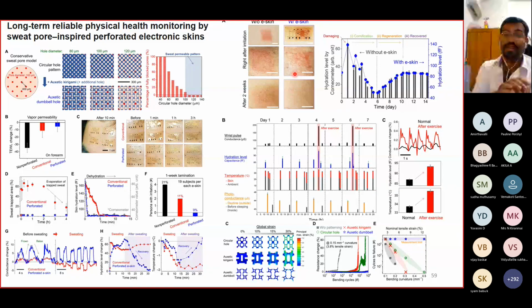So people are working on some perforated structures like this, but in our fiber case, we don't want all this. They also try to optimize the holes like this. They compare three different structures and optimize their strain conditions. They study the resistance changes and do bending cycles. And from this study, they are able to say that dumbbell shapes are quite good for the application because their stress-strain distributions are quite low. So that can be useful for very long-term cycles. Their durability is quite good, and that is what they are demonstrating. This one is published in Science.